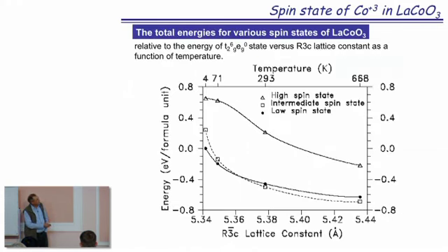Now, we imitated temperature purely by lattice structure parameters. So you see, here you have temperature, but below it just lattice parameter. And this small change of the lattice parameter, extension of lattice parameter, when your lattice expands, your distance between atoms increases, hoppings also decrease, crystal field splitting decreases.